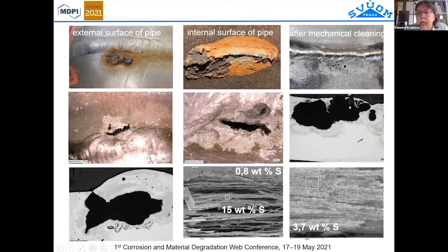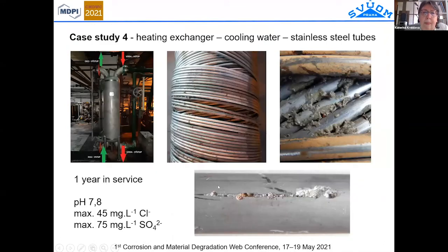We look at the morphology of the pits, which are also very typical for microbiological corrosion, and inside the pits we identify a high amount of sulfur, opposite to the layer of the other surface which was not corroded and where the content of sulfur is relatively low.